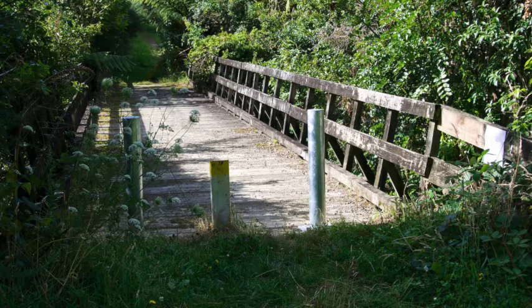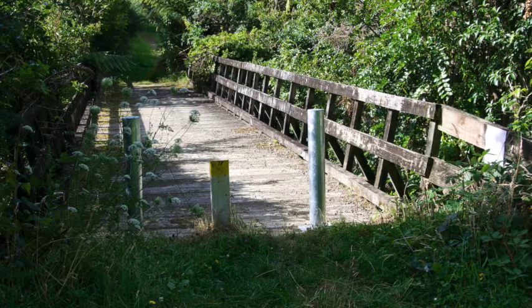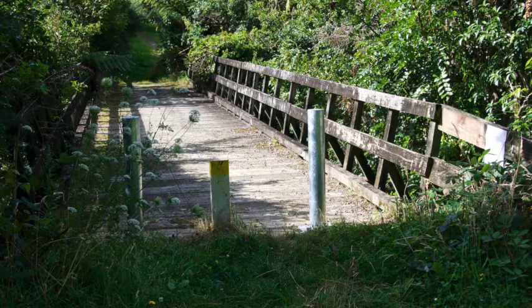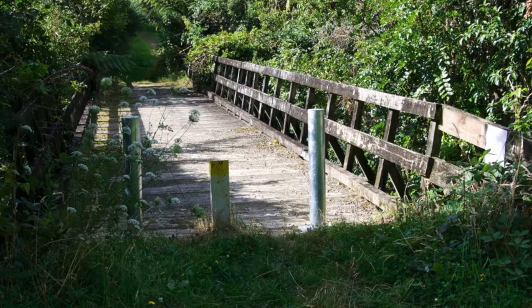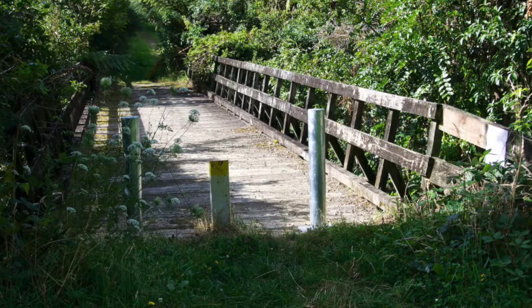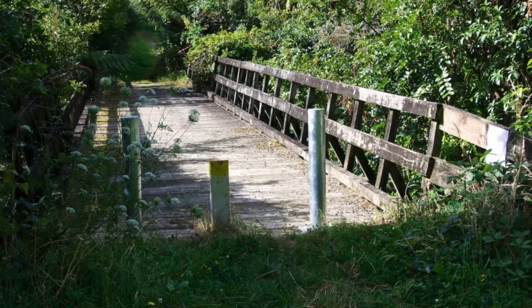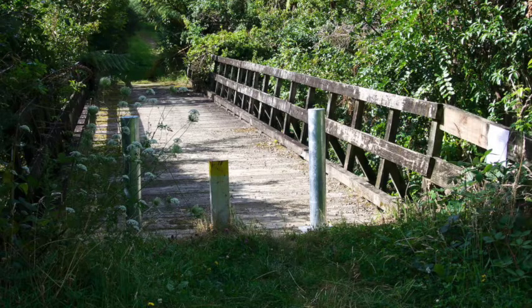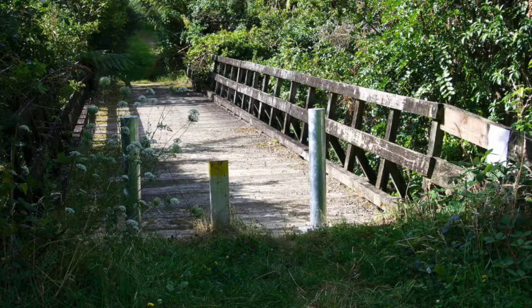Put another way, on average we would expect an exposed section of the Bad Bridge with no corrosion protection and no debris in contact with it would degrade at an average rate of about 0.01 millimetres per year. And it would take about 100 years on average to lose 1 millimetre of steel. Why are we so interested in rust and the rate at which it develops? Simple. The Bad Bridge is full of it, as you will soon see.